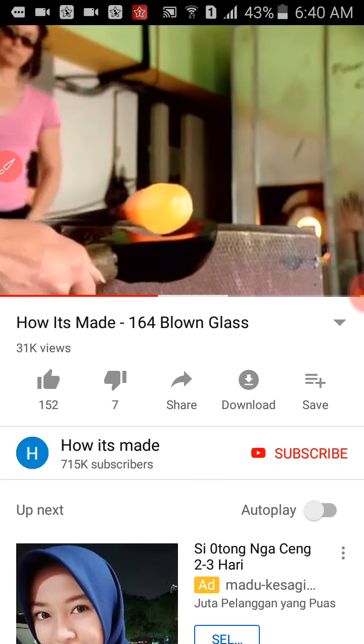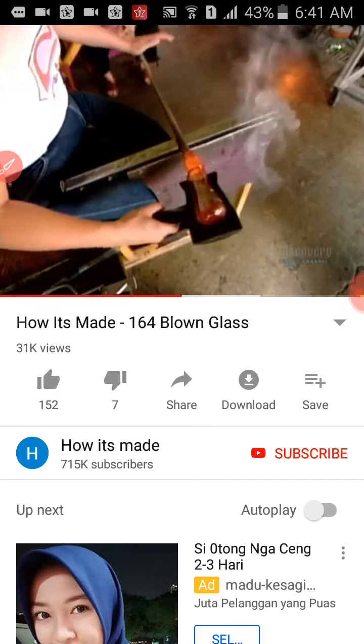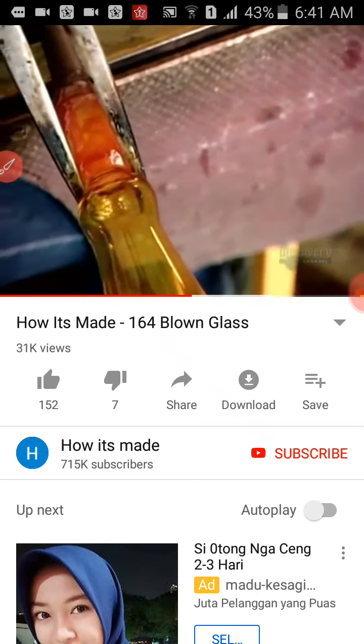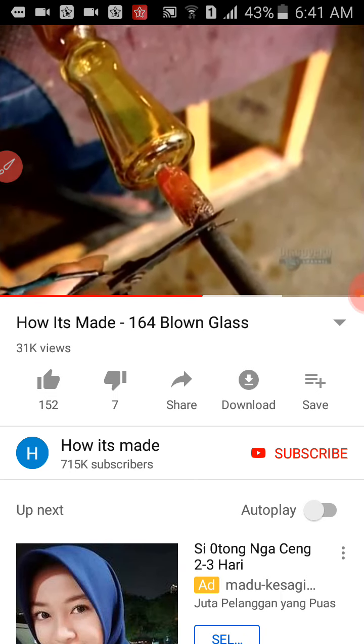Next, she rolls the glass against a ladle-shaped block to form a starting shape for blowing. A gentle blow or two bulges it into a hollow bubble. By now, the cooling glass has thickened to the consistency of caramel, making it more controllable and shapeable. The glass blower stretches and shapes the glass with different blocks and hand tools. The glass is like hardened caramel now and holds its final shape. She scores the glass where it meets the blowpipe, then cools it further with compressed air. On the opposite end of the glass, with a bit of hot glass, she attaches a solid metal maneuvering rod called a pontil. Then she applies a single drop of cold water on the score line to crack and break the glass off the blowpipe.